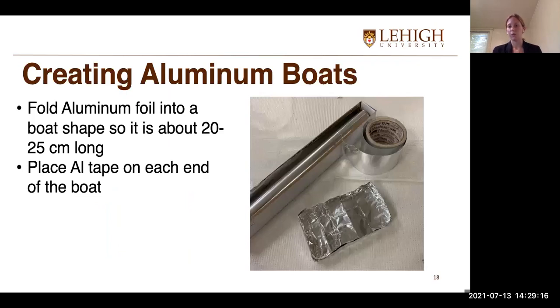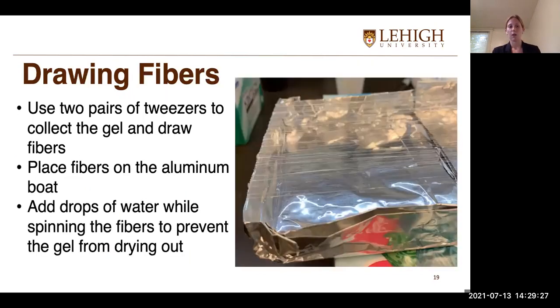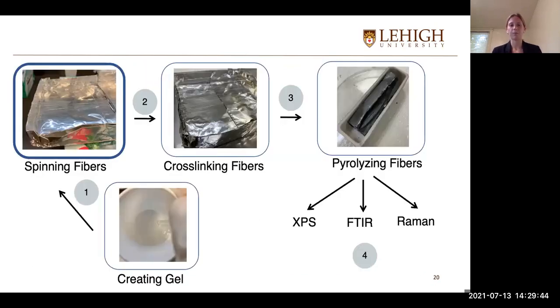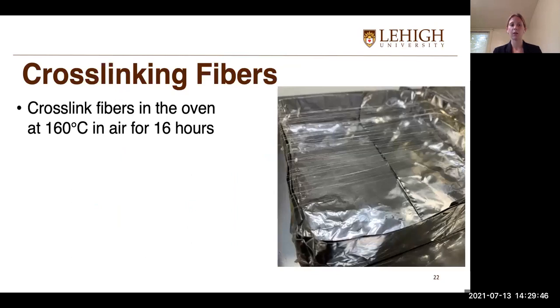To begin, I created aluminum boats by just folding aluminum foil into this boat shape. So it's about 20 to 25 centimeters long, and then placing the aluminum tape on each end. And then I would draw the fibers using 2 pairs of tweezers and place them on the aluminum boat. As you can see here, they just stick to the aluminum tape. And while I was spinning the fibers, I usually added a few drops of water to prevent the gel from drying out. So next, I'll talk about cross-linking.